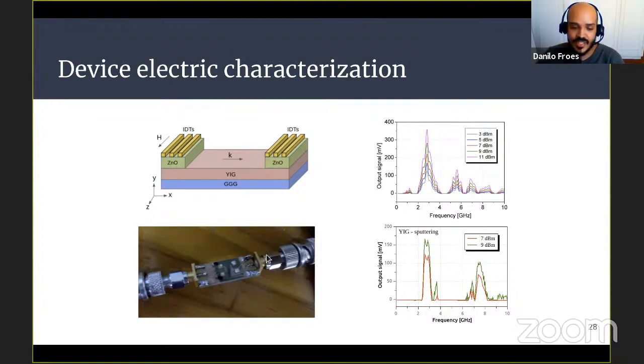Then we did some electrical transmission measurements. The input IDT was connected to a radio frequency generator. The output was connected to a rectifying diode and a voltmeter, and we measured the output signal while exciting the input one. For our bulk YIG, the liquid phase epitaxy one, the low damping one, this is what we got. This series of peaks here, we were very excited. We were like, okay, we're doing acoustic excitation. But in the sputtered YIG, we only have these two peaks, which was a bit of a warning. We are very cautious. Maybe we're not doing acoustic excitation, because we have these very different results. Even with the ZnO being the same, we're having very different results. So we were very worried.